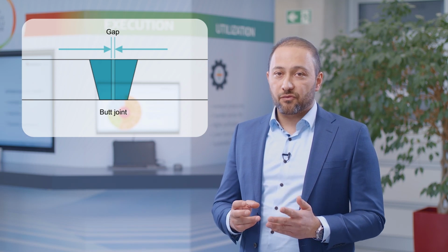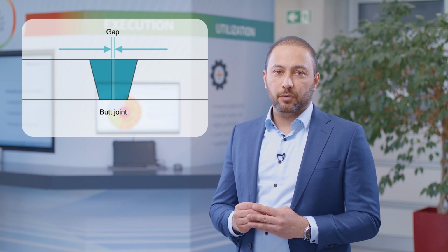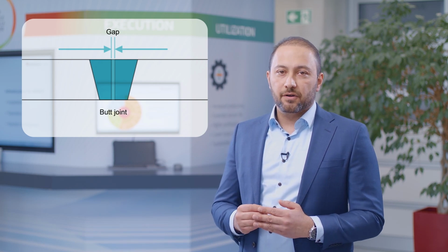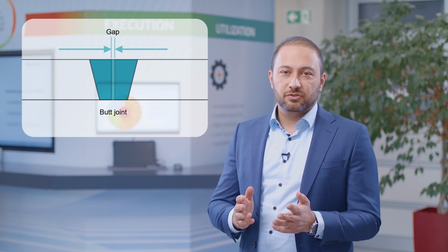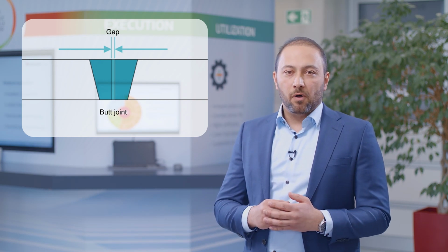Friction stir welding is performed without filler material. Therefore, if there is a gap between the joining partners, this may lead to either a seam underhang, reduced seam strength, or in the worst case, to pores in the weld seam due to the volume constancy. For an optimal result, the resulting gap width may not exceed 10% of the welding depth. This should be considered when designing the tolerance chains.